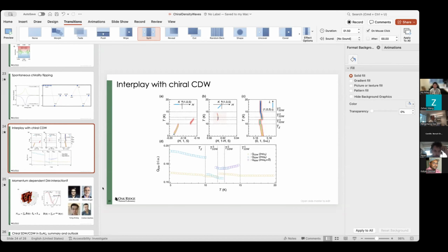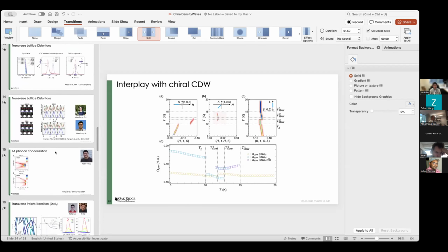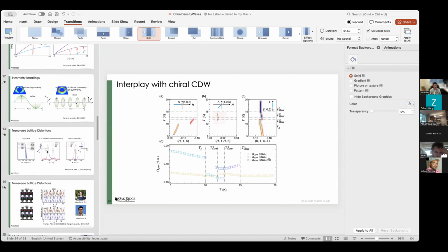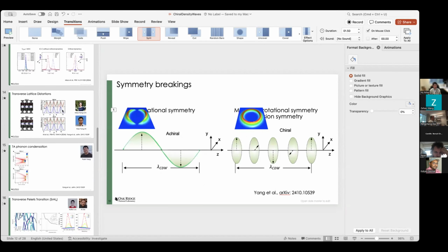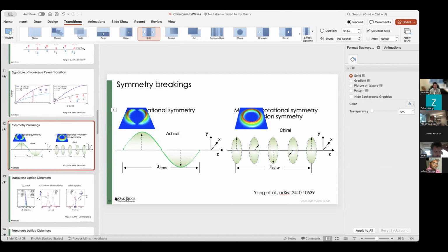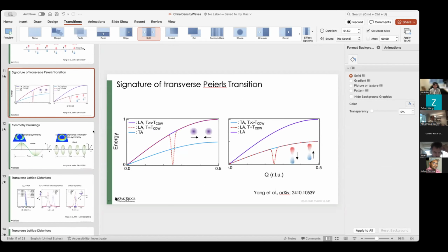We don't fully understand the microscopic driving force. Initially, I thought so. If you start from the transverse Peierls transition picture, Shidai had a paper saying that if there's a chiral phonon and a topological band structure, then you have to preserve the pseudo-angular momentum, and then you might be able to stabilize a chiral density wave. I don't know if that's true or not, but it could be a possible scenario.